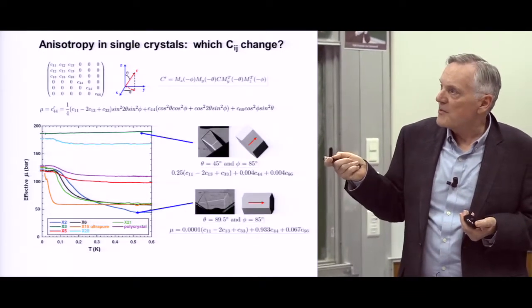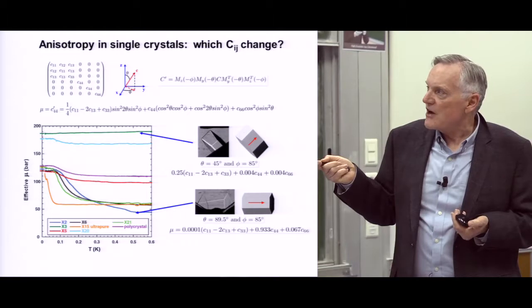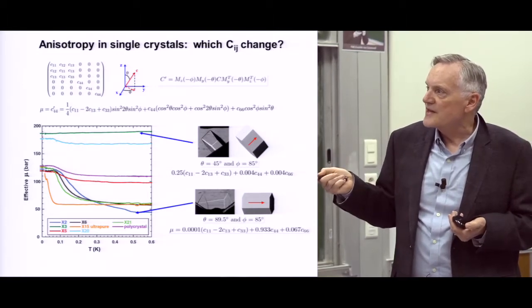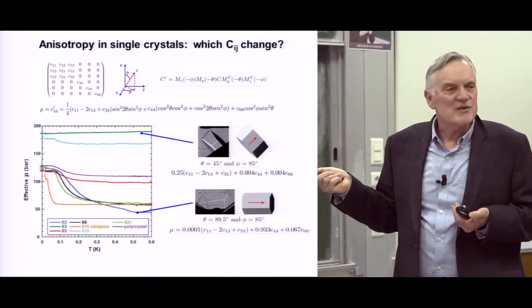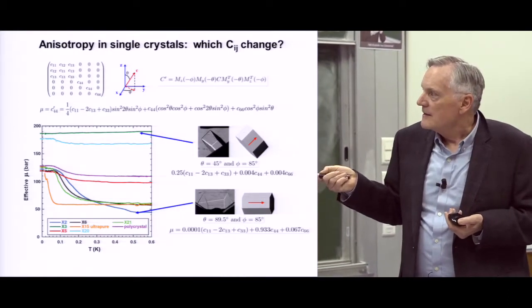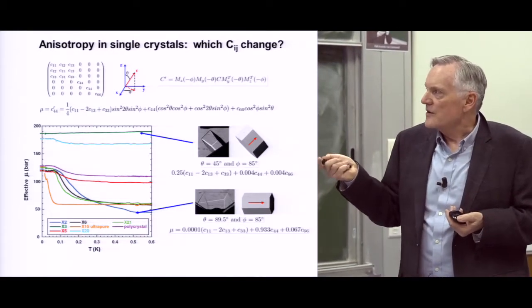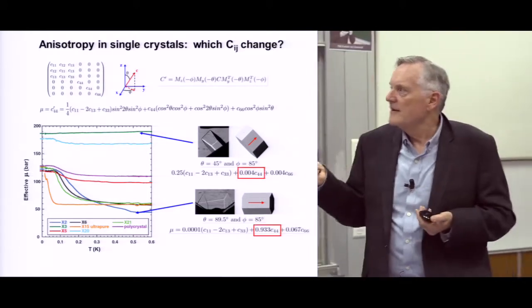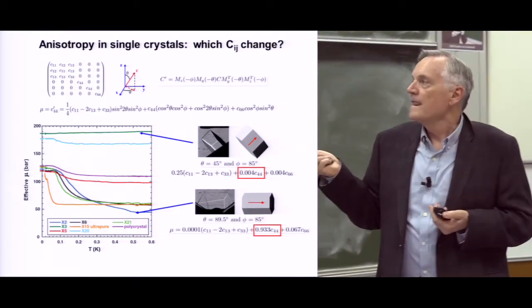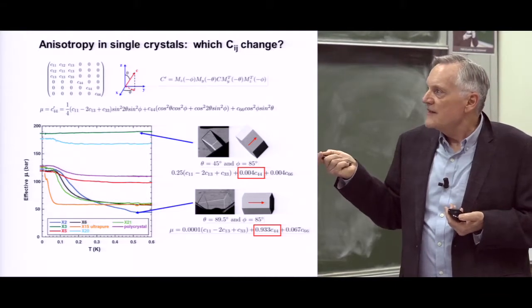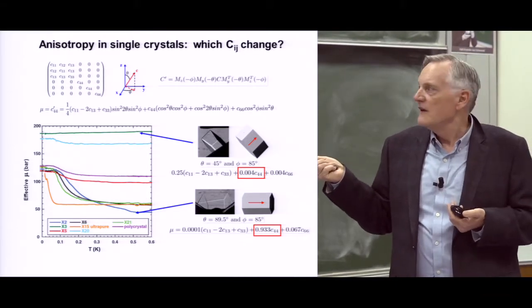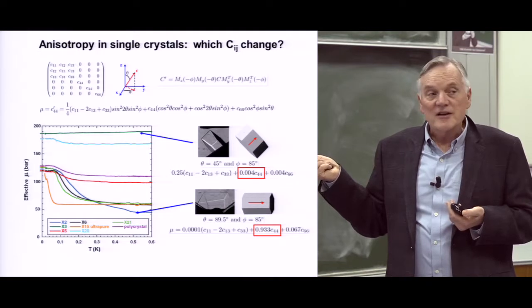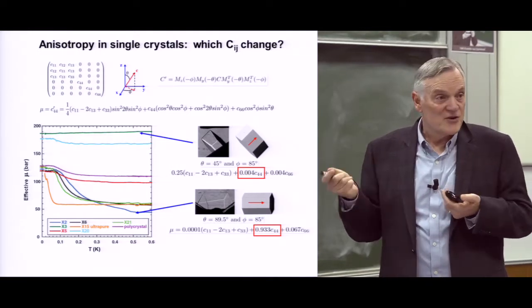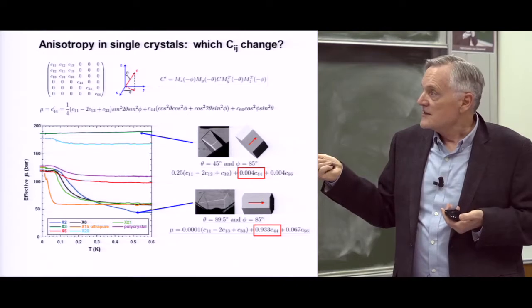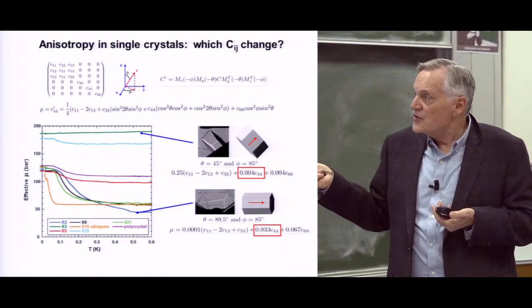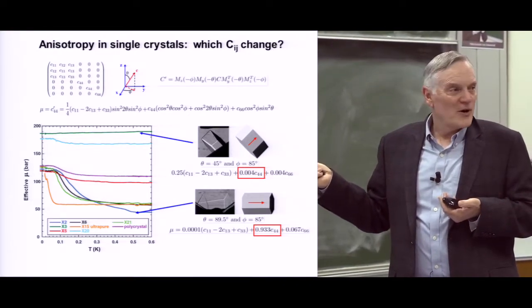And for example, if you take the one that's stiffest and never softens, that's the one at almost exactly 45 degrees. If you take the one that softens the most, that's the one that's almost horizontal at 0 degrees, 90 degrees, I guess, the way the coordinates are. And the interesting thing about that, again, you probably won't be able to tell, is this big messy expression. This orientation is the one orientation that the measured shear modulus does not depend on C44, the shear modulus in the basal plane. And this one, where you get a huge softening, it's all C44 and very little else.